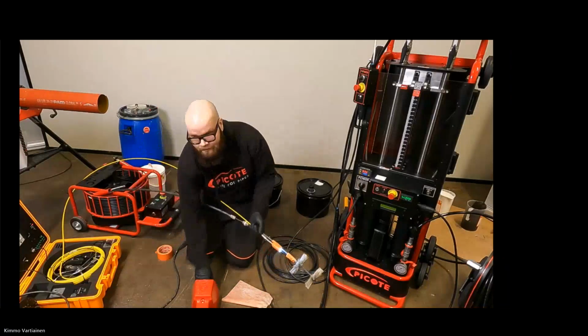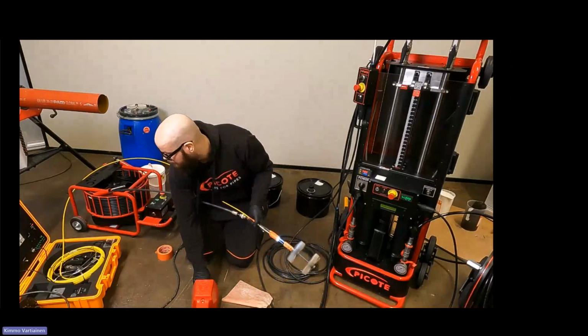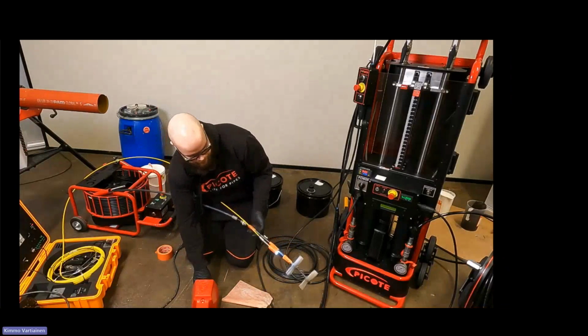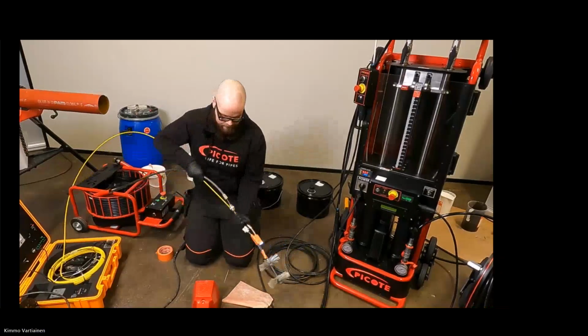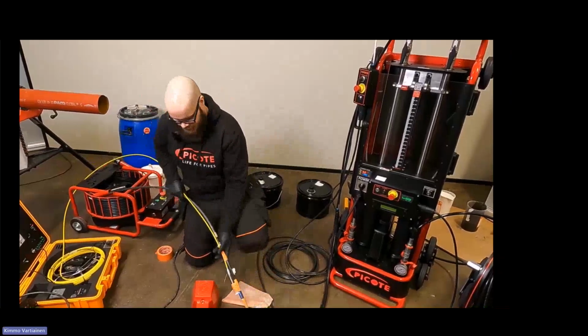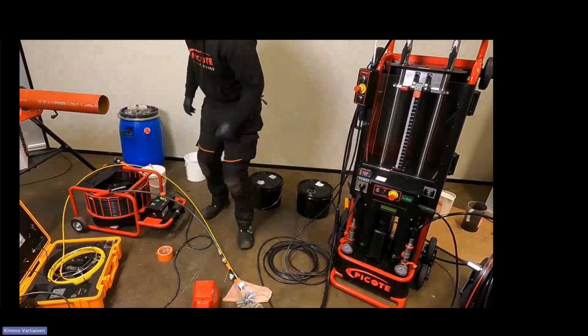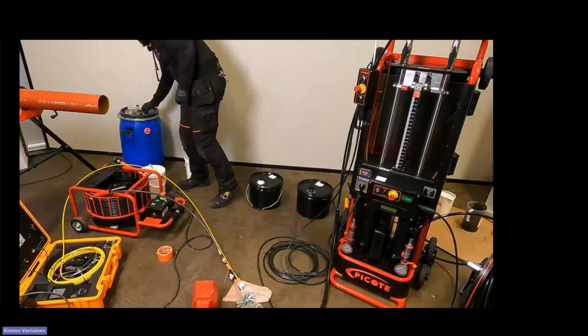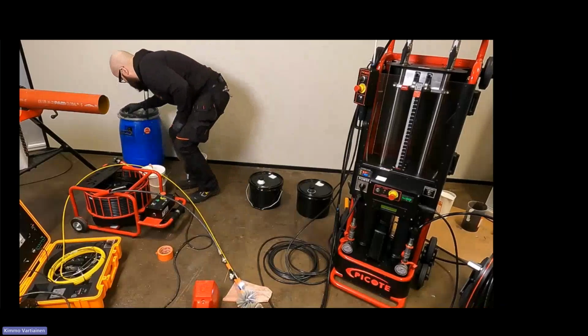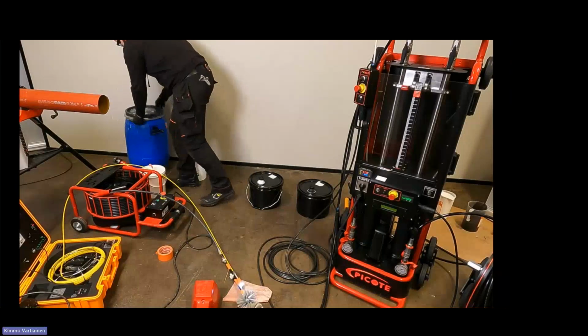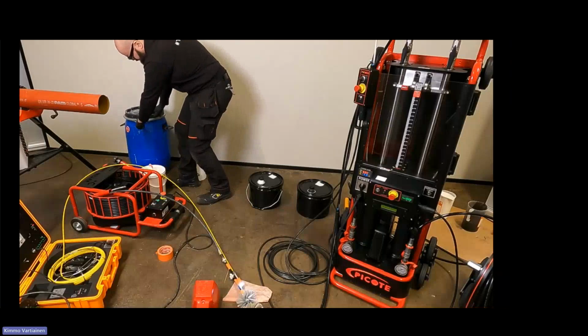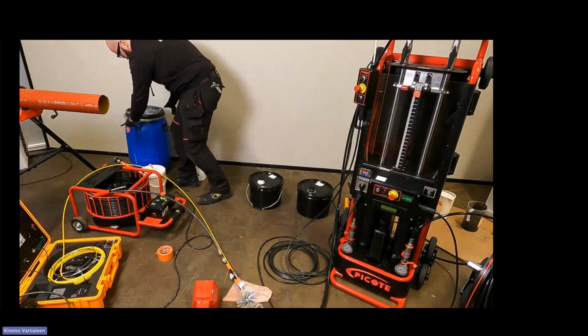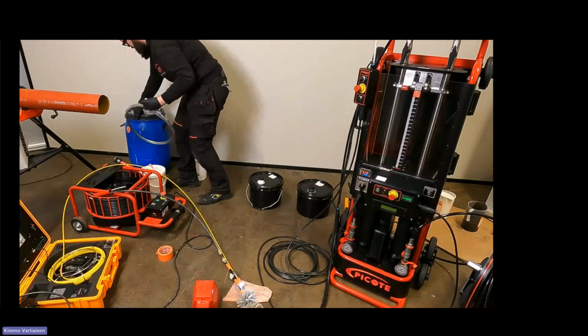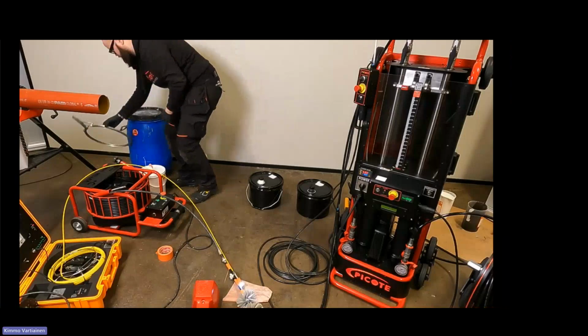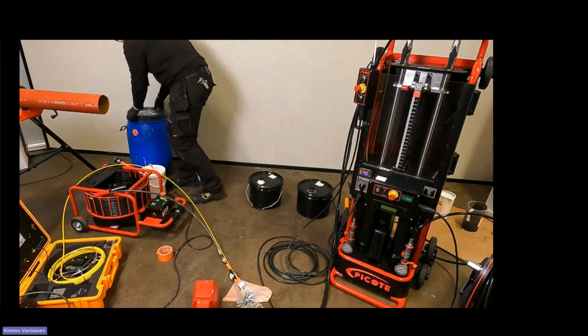And we always make sure the camera is just behind, so we can see exactly the tips of the brushes when it's inside the pipe. And the idea is that once we start mixing and pumping the resin, within seconds it comes out through the static mixer, and it runs onto the inside of the pipe, and then we spin the brushes up and apply the resin to the inside of the pipe.